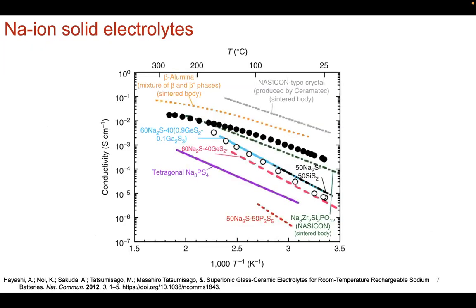So I also wanted to talk about the differences, the comparison of sodium-ion solid electrolytes with lithium-ion solid electrolytes, which we spent a lot of time talking about. So here you see the conductivity plot as a function of temperature. Here's reciprocal temperature, but here's temperature in centigrade. And we talked about the beta double prime alumina sodium ion conductivity, and it's quite high.